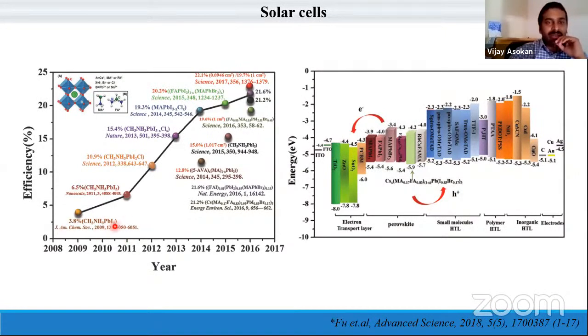It started from using PbI3, and sometimes there is incorporation of ammonium within the perovskite material, or changing the ratio of iodide and chloride. Then, instead of methylammonium, formamidinium can be used, and instead of iodide, bromide can be used. With each of these different arrangements, the efficiency kept on increasing from 3.8 towards 21.6% in 2017. So it is useful in such a way that you can play with different materials or combinations, starting from the basic methylammonium lead iodide structures towards bromide and formamidinium structures.